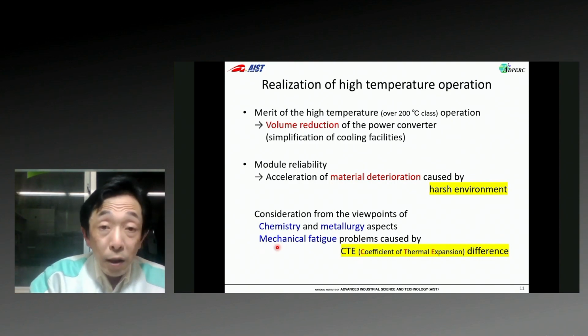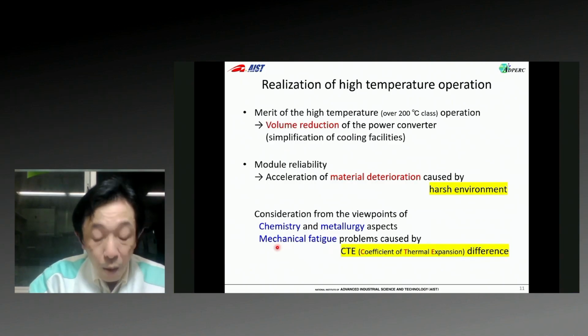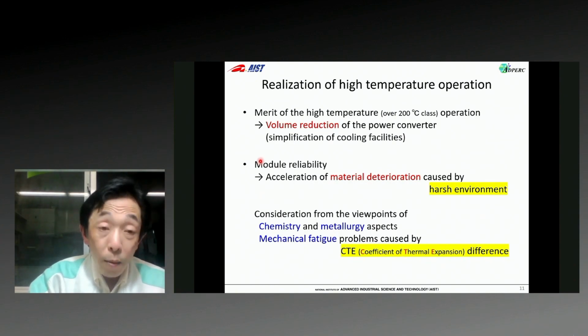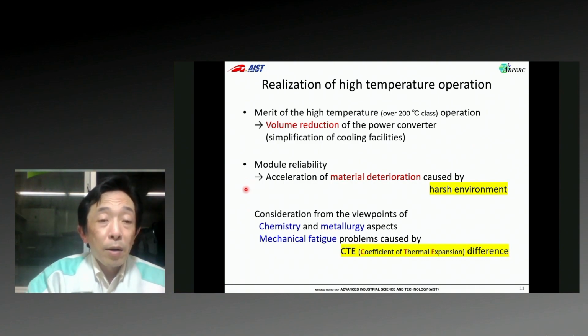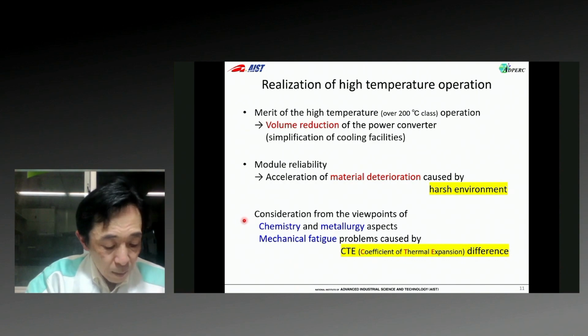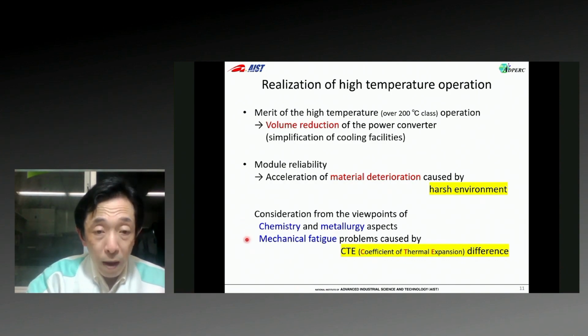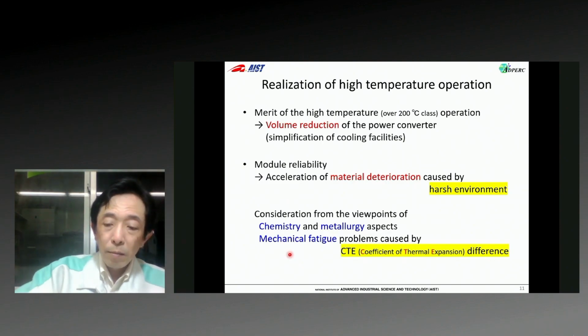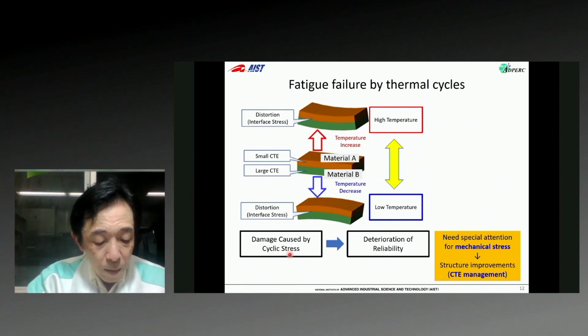Another expectation of SiC power devices is high temperature operation over 200 degrees Celsius, which cannot be realized by silicon power devices. The merit of high temperature operation is a reduction of the cooling facilities. However, reliability is the biggest issue for the realization. This problem should be considered from the viewpoint of chemistry and metallurgy. In addition, the mechanical fatigue problem, which is caused by the difference of CTE, should be carefully considered. The fatigue failure problem is caused by the CTE difference and the fluctuation of the temperature.